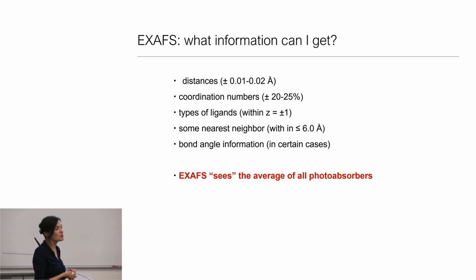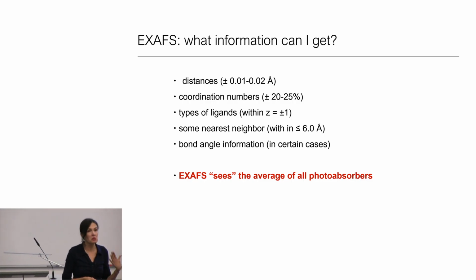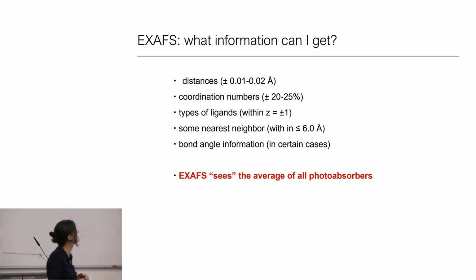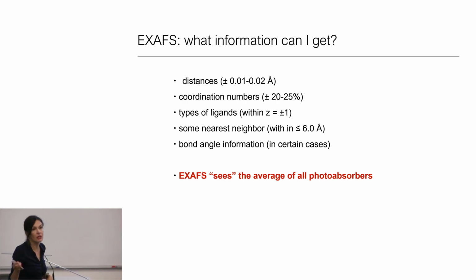This means, as with almost any scattering method, carbon, nitrogen, oxygen, they all kind of look the same. And so you need other input to distinguish those. One of those is valence-to-core X-ray emission that my group has been quite interested in. You can also get some nearest neighbor information.